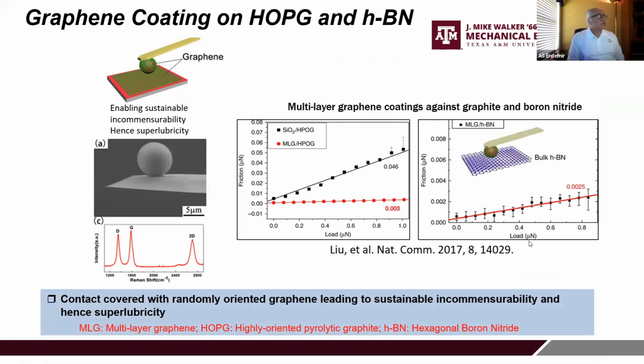And this effect was not limited to very conformal surfaces. It could also be achieved with graphene applied to a microsphere, rubbed against either graphene or graphite. You can see the difference in this article: silicon dioxide microsphere against highly oriented pyrolytic graphite shows, with increasing load, very high frictional force.